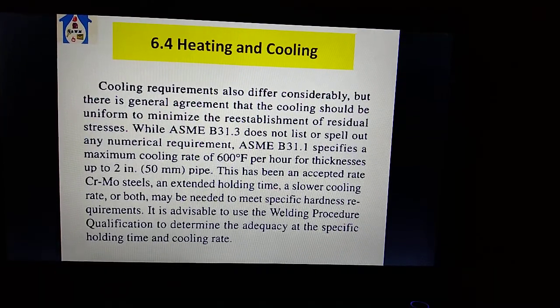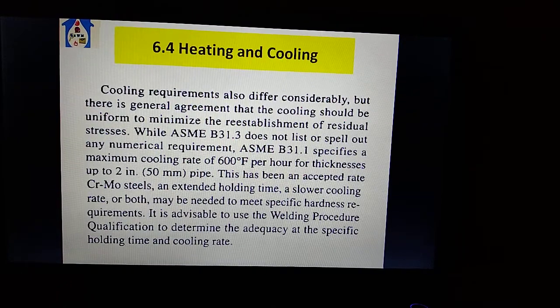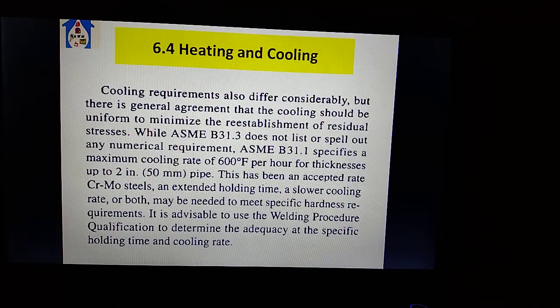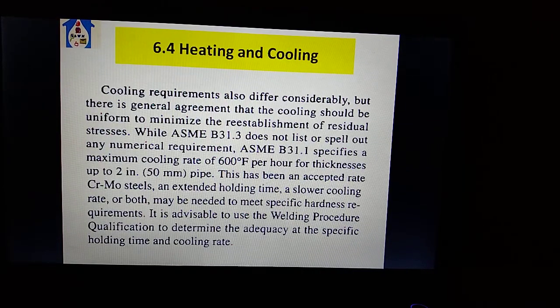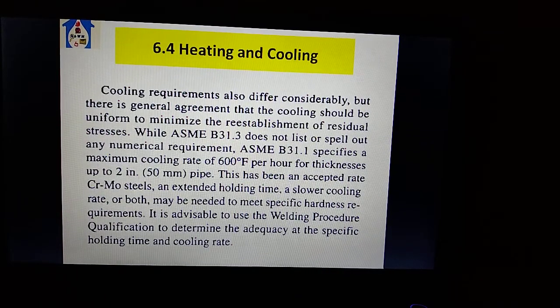Heating and cooling. Cooling requirements also differ considerably, but there is generally agreement that the cooling should be uniform to minimize the re-establishment of residual stress. While ASME B31.3 does not spell out any numerical requirement, ASME B31.1 specifies a maximum cooling rate of 600 degrees Fahrenheit per hour for thickness up to 2 inch, 50 mm pipe.